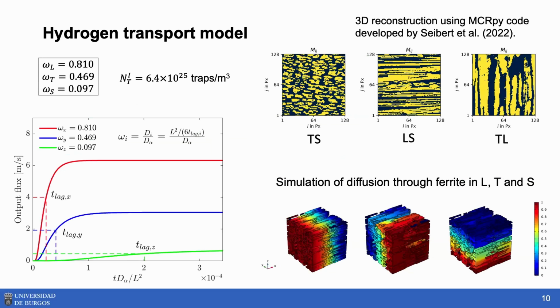This is the 3D reconstruction I was talking about before. This is very simple. We are just taking slices from the optical microscope, 3 orthogonal slices. We input these slices into a reconstruction code, which uses optimization of the descriptors for this geometry. And you get a 3D reconstructed geometry that represents your real unit cell for this elongated microstructure. We put this 3D unit cell into COMSOL Multiphysics with a simple diffusion model, and we are able to calculate the tortuosity factors, just accounting for the percolation and the connectivity of each phase. As we were expecting, in the longitudinal direction we are closer to 1, and in the thickness direction we have a very low value because the path is very tortuous.